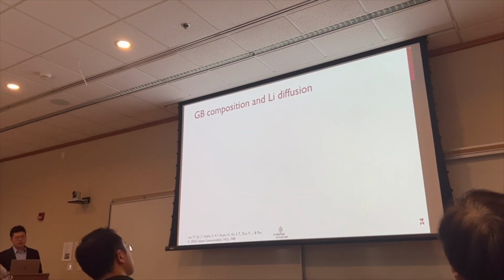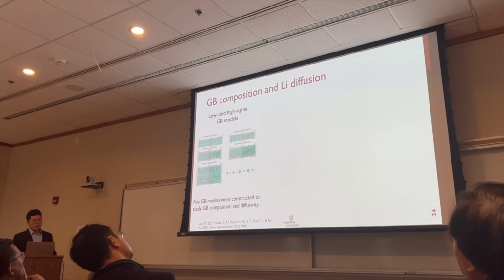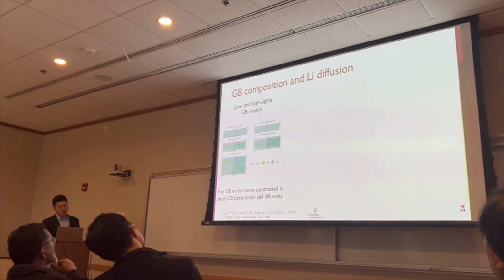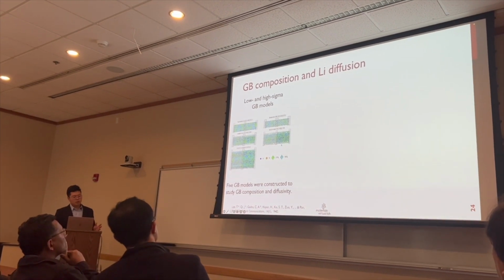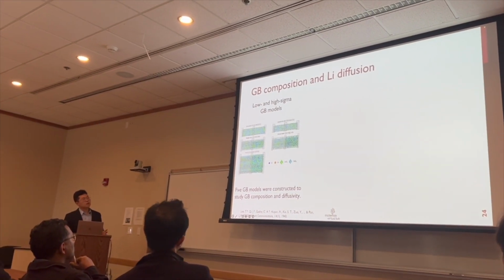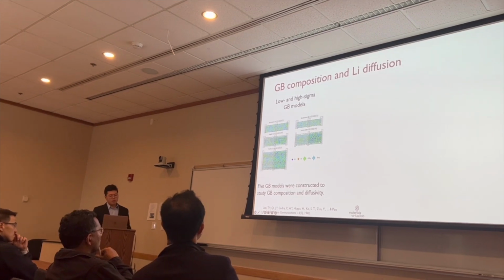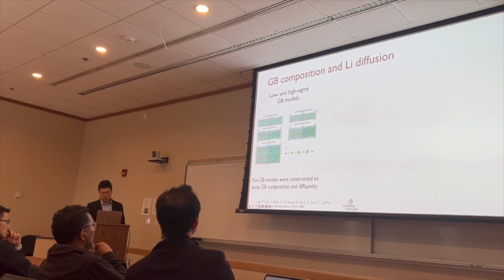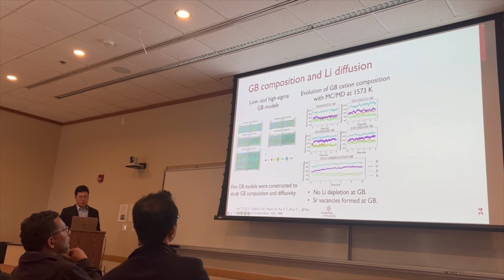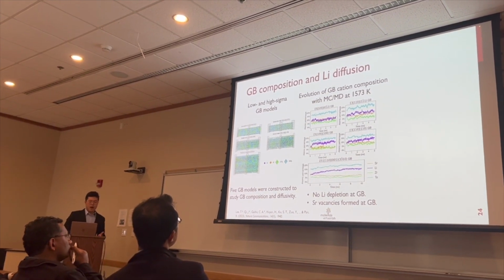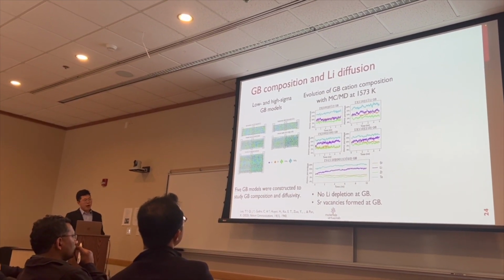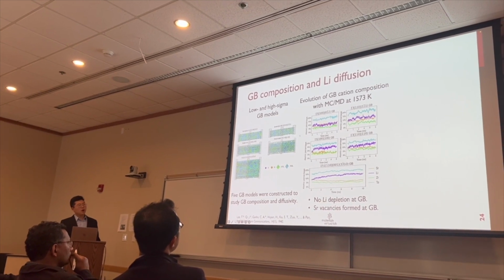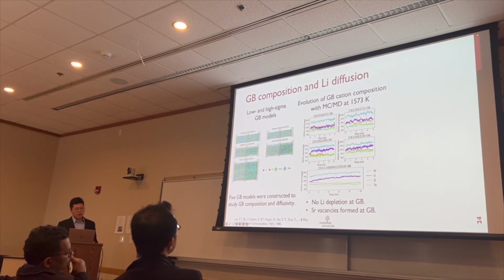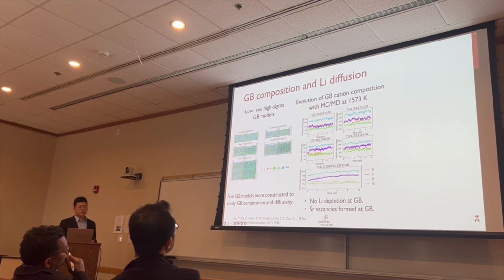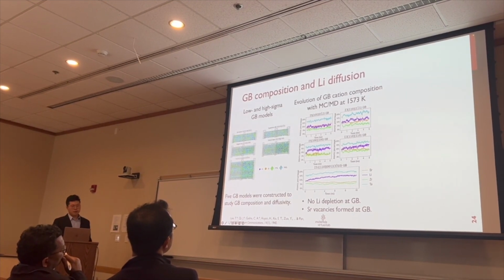We then apply the model to study the grain boundary composition and lithium diffusion. In our study, we have 5 grain boundary models. 4 of them are low sigma grain boundary models, and the other one has a relatively large sigma of 51 to mimic a general grain boundary. And we again applied hybrid Monte Carlo molecular dynamics simulation at the experimental calcination temperature of 1573 Kelvin to observe the evolution of grain boundary cation composition.